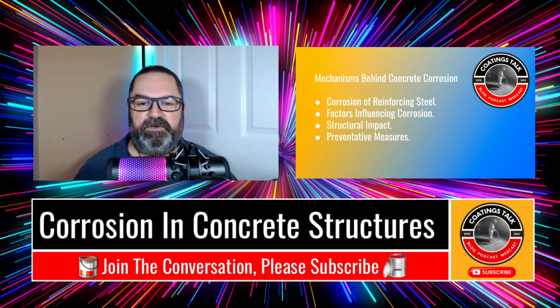Now, for preventative measures, you have coatings and sealants. You want to apply protective coatings or sealants to prevent moisture and chloride penetration. Cathodic protection: the use of impressed current or sacrificial anodes protects rebar from corrosion. High alkaline concrete: design concrete mixes with high alkalinity, and this would be a pH of 12.5 or greater to maintain passivation of steel. And then proper cover thickness.